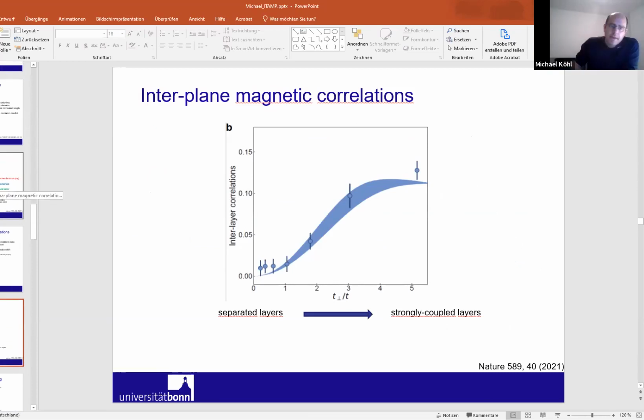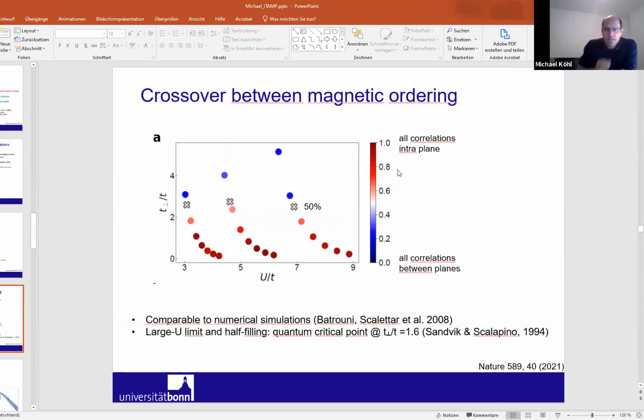So the question is, how do you compare these numbers that we assign to these vertical axes? No, how does the correlation compare in the bilayer system compared to just one layer system, the correlation between different sides? Okay, that is basically shown on this graph. We've normalized this appropriately, and now if the data point is 1, then we have 0 correlations between the planes, and down here is the opposite. You can see how this behaves as a function of the interaction. But if we take the same normalization, it seems that intraplane you reach a correlation that you label as 1, but in between the different planes you saturate to a lower value, I think 0.1. Do I understand correctly? Yes, sort of.